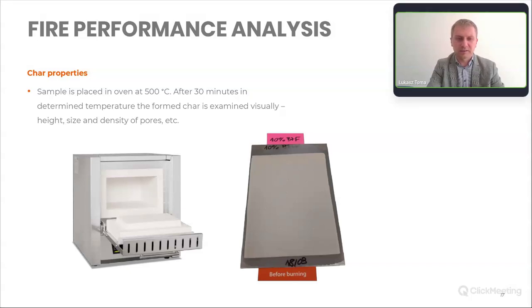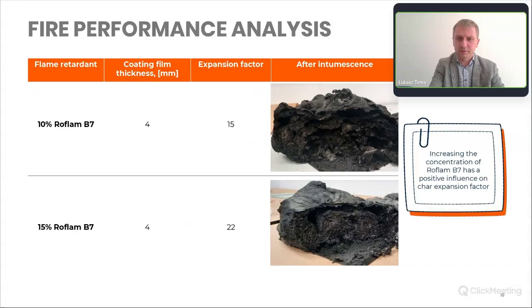Mostly we are talking about the size and the density of the pores, but we can also assess the expansion factor of the char. And on the next slide, you see the results for the formulation with 10% of Roflam B7 and 15%. That is the optimum range I mentioned on the previous slides. The effect on pore size and density is similar, but there is a positive influence on the expansion factor. So we have higher char in this case, and we see this supporting effect of our Roflam B7 on this parameter.